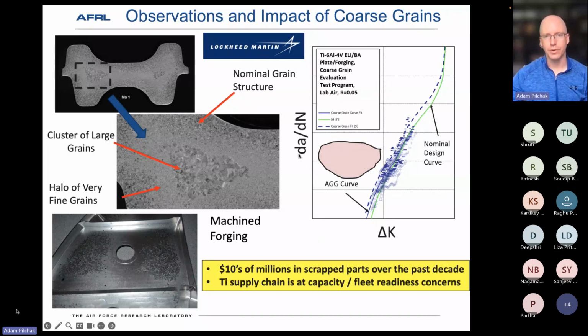In the upper right here, numbers are removed, but showing a kind of classical fatigue crack growth curve. So da/dN, crack extension per unit cycle. And on the bottom here is delta K, stress intensity factor range, which you can think of as the driving force for crack growth. A lot of the airframe structural components are designed and managed to, at least in the Air Force, a damage tolerance requirement. So the first thing people are ultimately interested in is what's the effect on the crack growth rate.